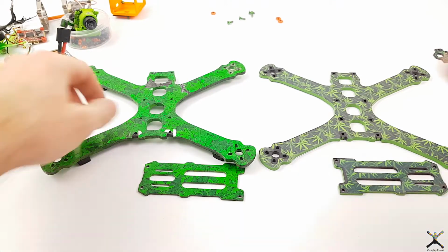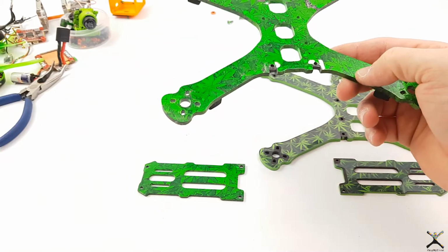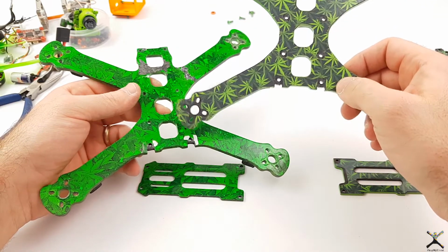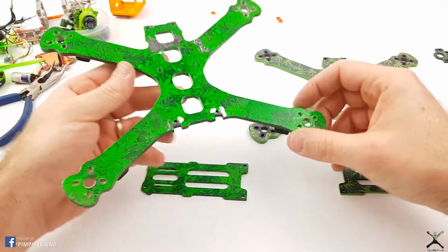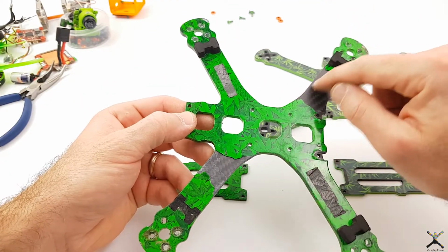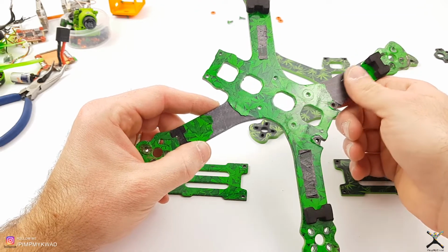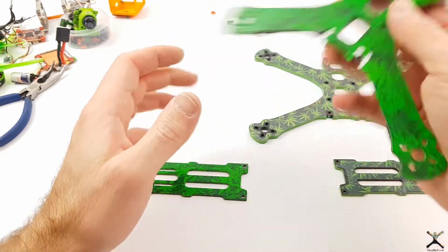The complete dismantling of the chameleon is done, and we can see that the colors are more vibrant and lighter on the hydrodipping. It's not really a problem because the patterns I used were different. So if I use a lighter pattern for the sticker, it will be fine. Hydrodipping here has suffered. I wanted to go faster when I hydrodipped this frame, and I didn't sand the frame. So the hydrodipping layer can now unstick and hook because the carbon is way too smooth, too slick.